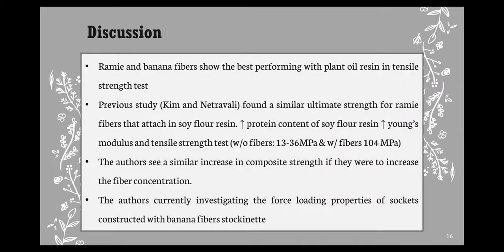For the discussion, the ramie and banana fiber show the best performance with the plant oil resin in the tensile strength test. And a previous study conducted by Kim and Netravali found a similar ultimate strength for ramie fibers attached in soy flour resins. Increasing the protein content of the soy flour resins also increased Young's modulus and tensile strength. They also tested with and without the fibers, and the authors saw a similar increase in composite strength when increasing the fiber concentrations.